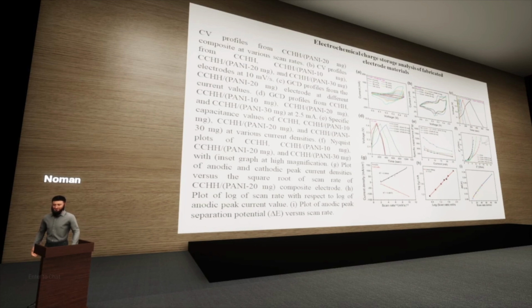At various currents, the capacitance changes. At high currents, the capacitance becomes low because the ions do not find the proper time to adjust themselves. So to find out the electrochemical impedance of the material and the electrolyte, electrochemical impedance spectroscopy was performed, which shows that the 20 milligram addition of polyaniline showed the minimum resistance for the charge and ions between the positive and negative electrode.